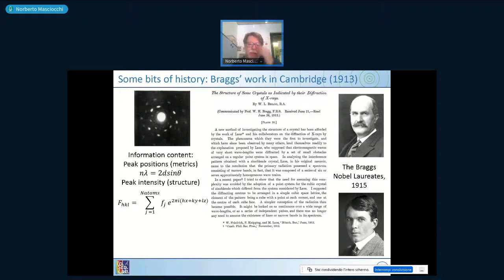One year later, Bragg's father and Bragg's son, the two got the Nobel Prize because they published a paper in which, using the images they could get from sodium chloride and developing some theory, the peak positions were related to d-spacing, that means the interplanar distances of a system. And the peak intensity is related to a formula, the structure factor formula, to the position of the atoms x, y, z, and the nature, f_j.